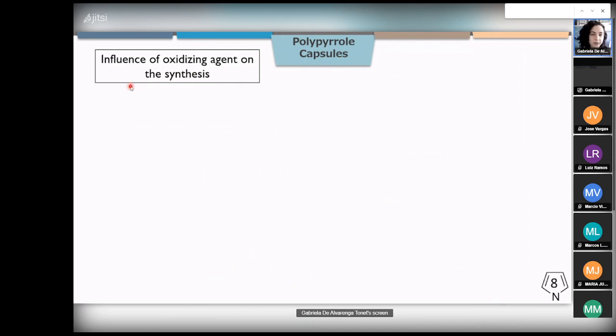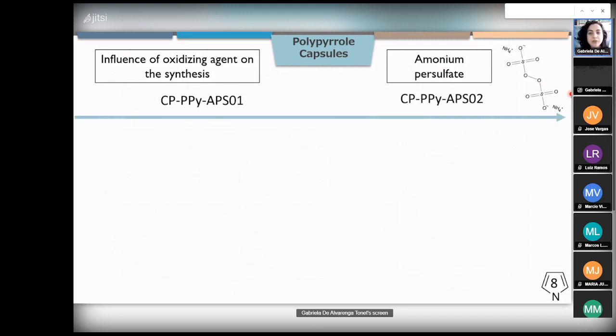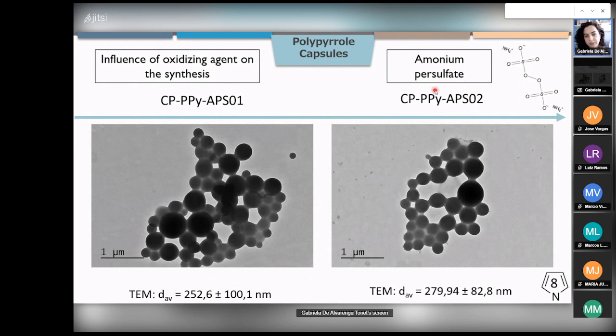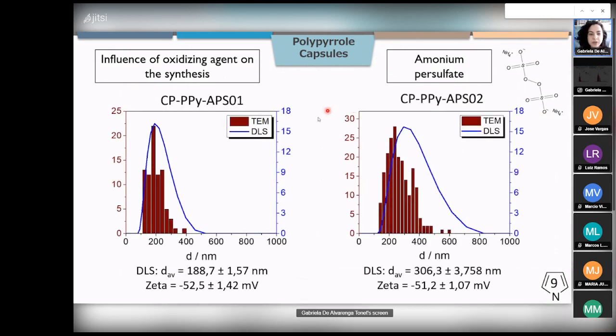So as a following step, we studied the influence of the concentration and the type of oxidizing agent on the morphology of the capsules. And we started by using ammonium persulfate, which is a common oxidizer to form polypyrrole. And we used 2 different concentrations. And we saw that, as expected, the more concentrated solution formed slightly bigger capsules. This trend was confirmed also with DLS measurements. So we measured the capsule size in TEM images and in DLS, and comparing those 2 measurements, they were in agreement. We could also see that the zeta potential of these capsules was negative, which is confirmation that the SDBS surfactant is being incorporated into the polymeric matrix.